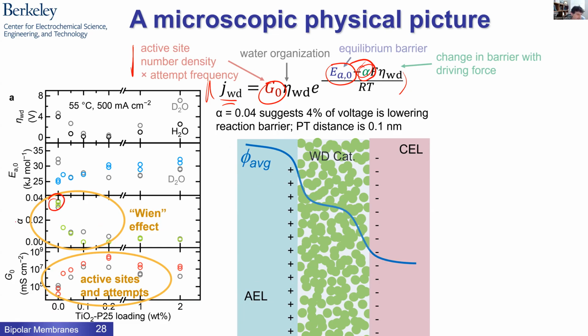So if you don't have any catalyst, alpha is not even close to 1. It's very small. Typically, alphas are about 0.5 in electrochemical reactions. We're seeing alpha of about 10 times lower. It means the potential is driving the reaction, but it's only having a very small effect relative to the total driving force drop. And the reason for that, at least we think, is that often in an electrochemical reaction you have a metal, and you have a double layer, and you're driving a charge across the double layer, and the charge transfer distance is commensurate with the distance of delta phi, the electric potential across that interface. Here, delta phi is developing over this much larger distance, and the protons are transferring over a shorter distance, right? So one might expect that the effect of the field would be substantially smaller, in fact, the geometric ratio of those distances is about 0.04.